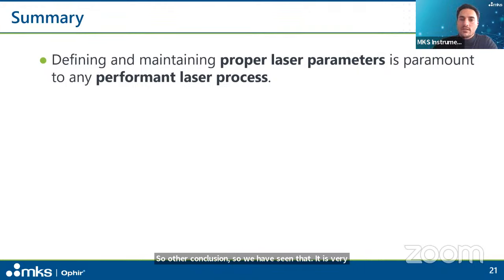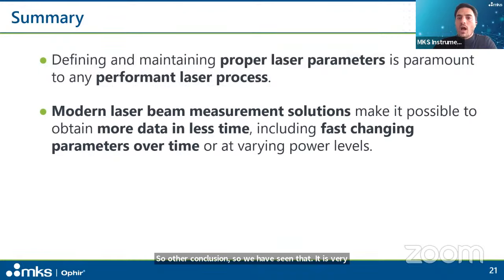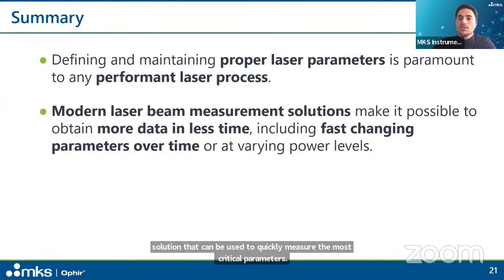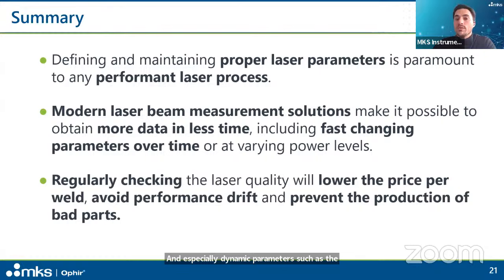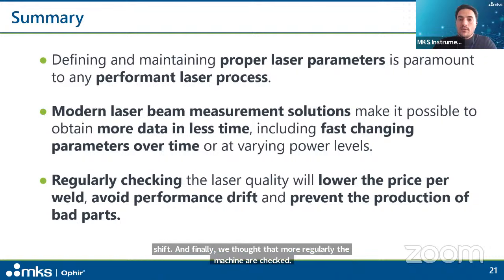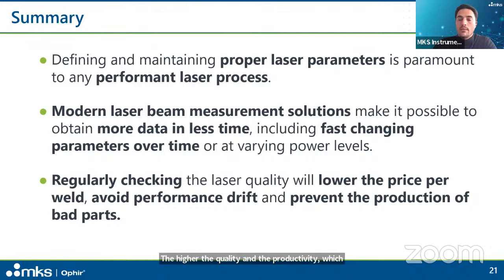So as a conclusion, we have seen that it is very important to know and maintain the laser parameters. We have also seen that there are specialized measurement solutions that can be used to quickly measure the most critical parameters, especially dynamic parameters such as the focus shift. And finally, the more regularly the machines are checked, the higher the quality and the productivity, which will help you reduce the price per weld.